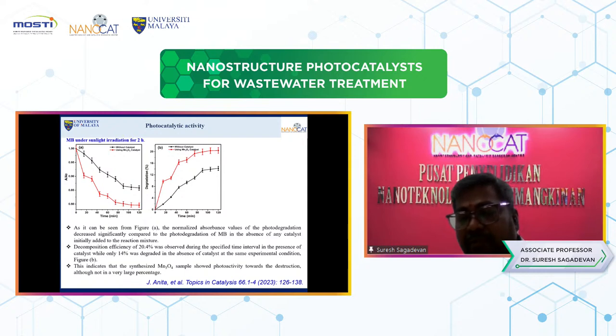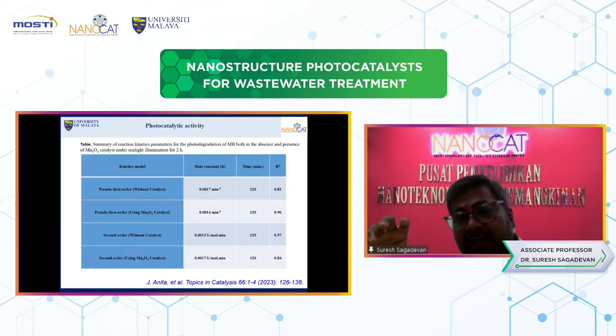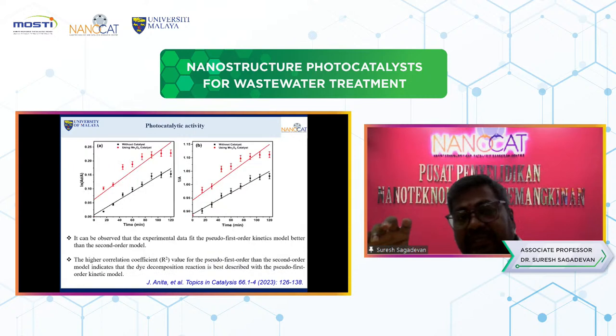The drop in the absorption peak of methylene blue was rapid in the early phases of contact, but it becomes slower as the process reaches equilibrium. Initially, the quick degradation was attributable to the huge number of active sites on the catalyst, but as these active sites were occupied, degradation became much less. According to the kinetic studies, it can be observed that the experimental data fit the pseudo first order kinetics model better than the second order model.